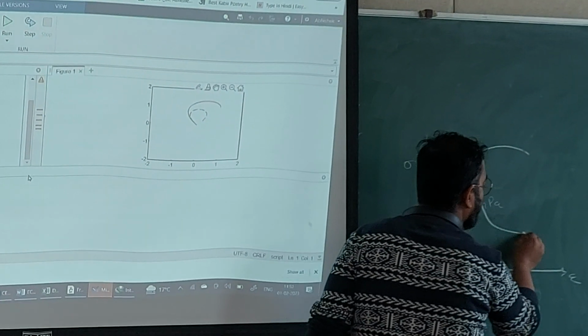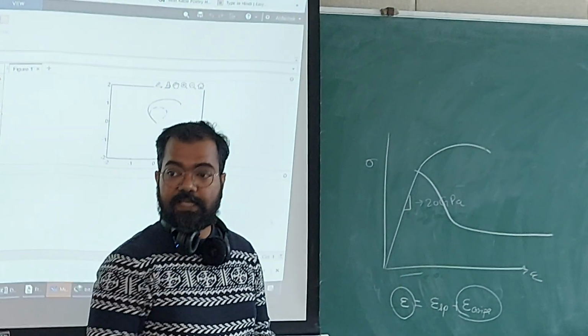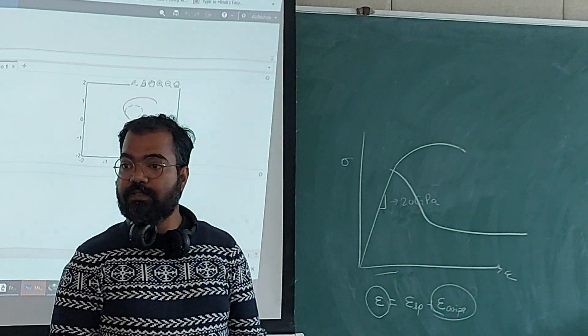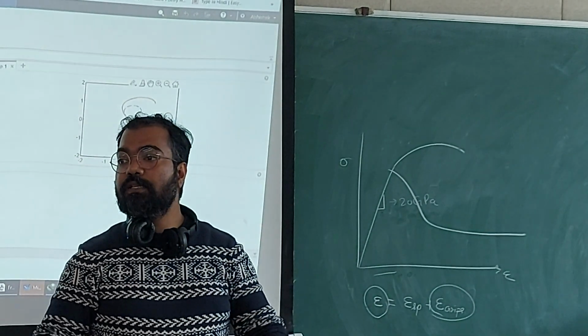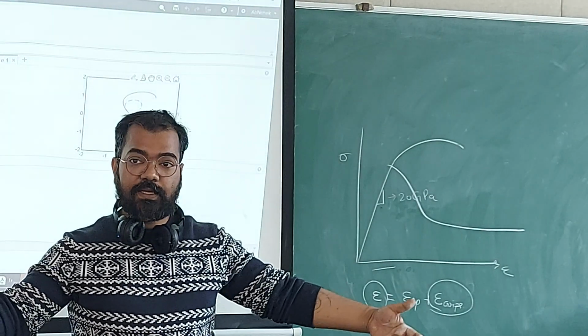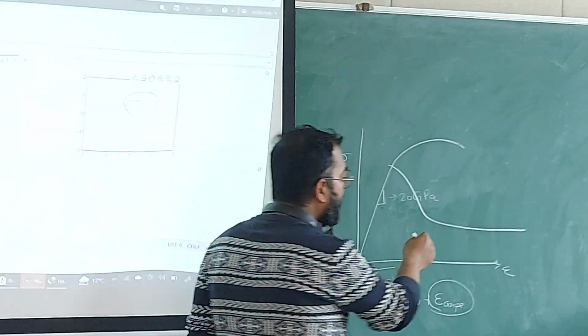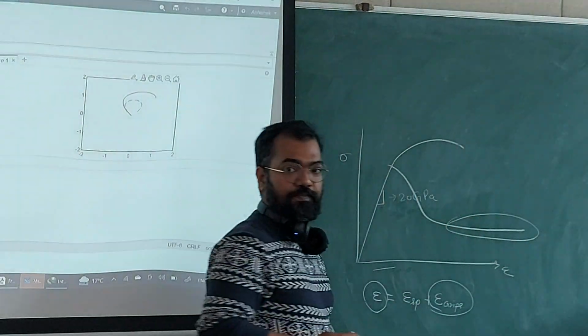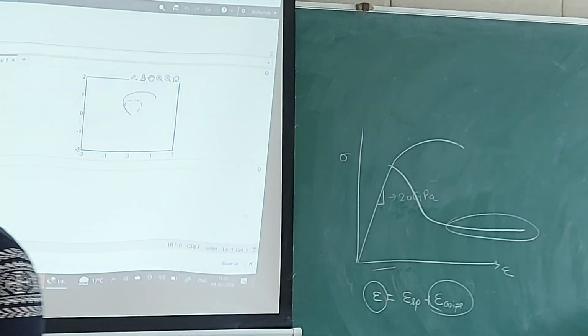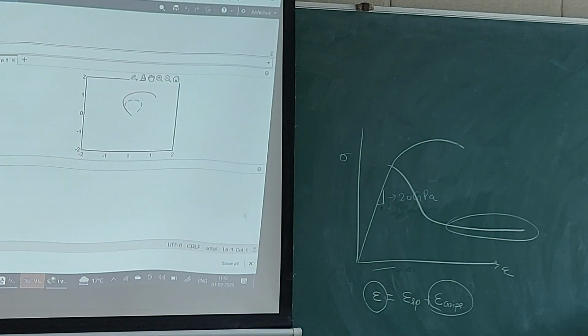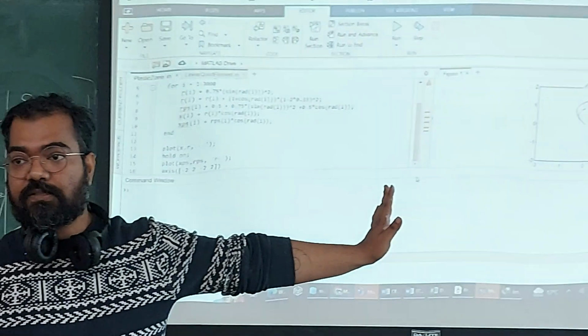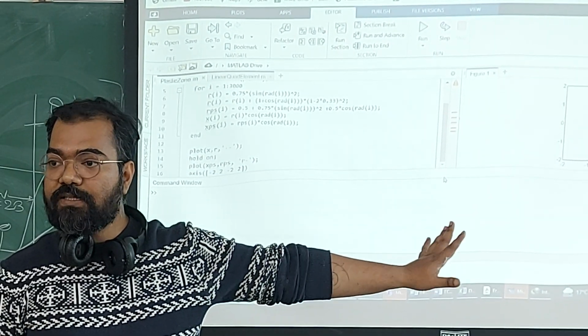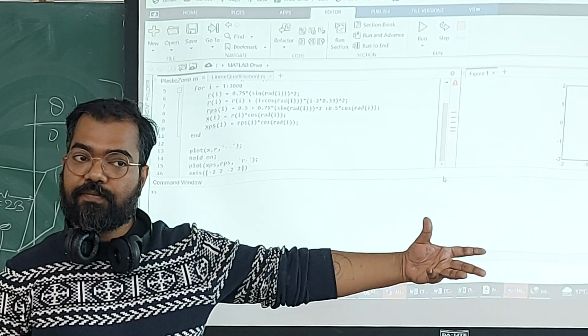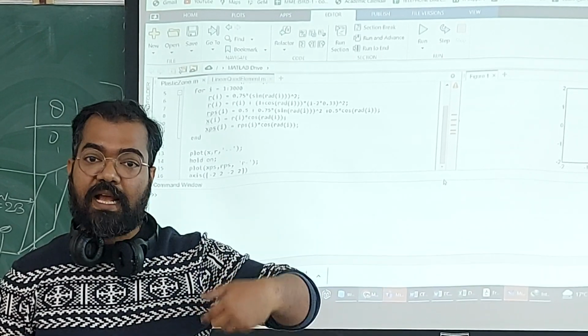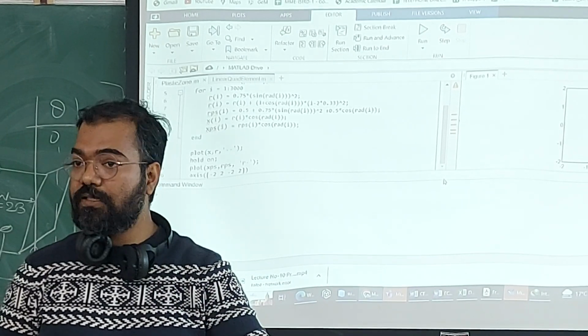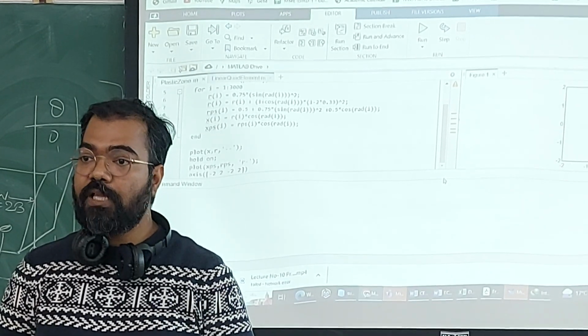that fracture toughness for a thicker specimen of the same material is smaller, and after a certain value of thickness it becomes constant, and only in that range is it a material property, because material property should not change with thickness. So beyond that thickness of plane strain, K1c becomes a material property. So the K1c which you calculate as a material property must be plane strain fracture toughness. You must ensure the condition of plane strain.